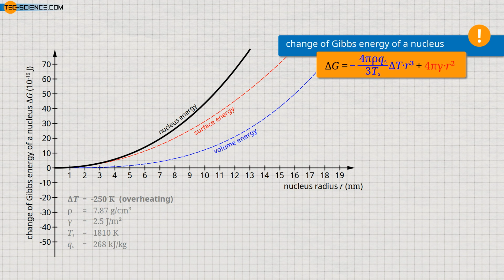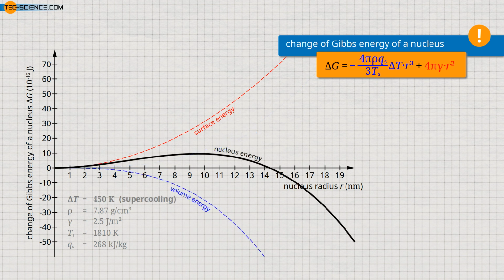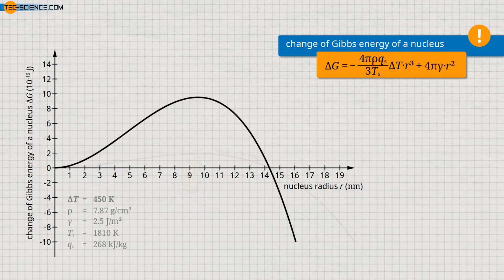However, the diagram only becomes interesting when the temperature of the melt or nucleus is below the solidification point and thus supercooling is present. In this case, the first term of the equation becomes negative. For this case, the diagram shows the course of the change in the Gibbs energy of the nucleus as a function of the nucleus radius. The curve now shows a maximum. This curve will be interpreted in more detail in the following.